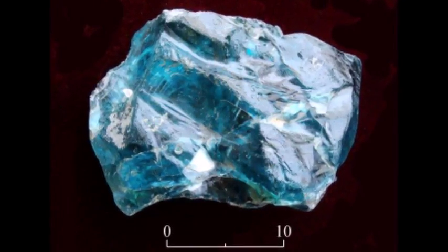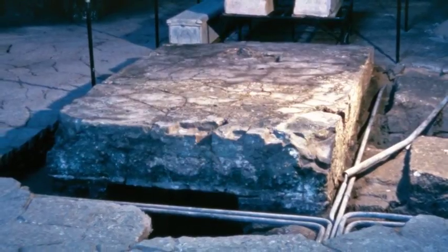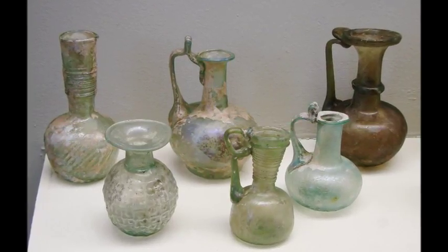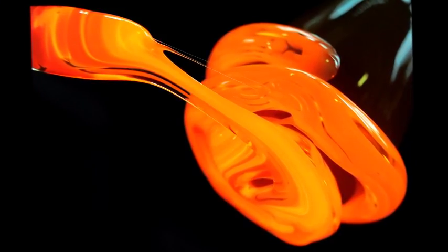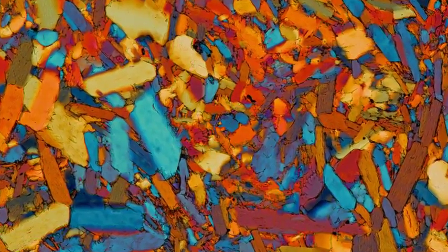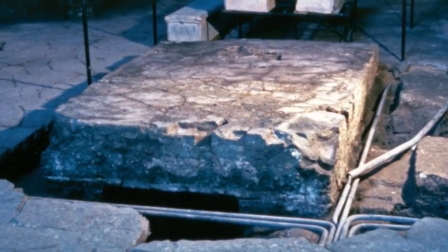The glass itself has blobs and bubbles and other evidence of its molten history, but the material does not look like glass. It is not transparent. We know why that is too. Chemical analyses have shown that whereas most of the glasses of that time contain about 8% lime, that is, calcium oxide, this glass contains twice that much. Apparently, some of the limestone, or the plastered arch over the tank, had become disintegrated by the heat, and sifted down into the molten glass as a chalk-like powder. We know that when glasses with excess lime cool slowly, and this glass must have cooled very slowly, the glass becomes partially crystallized. The myriad tiny crystals, visible through a microscope, turn the glass opaque. That is probably why the glass was never broken up to be used for making vessels.